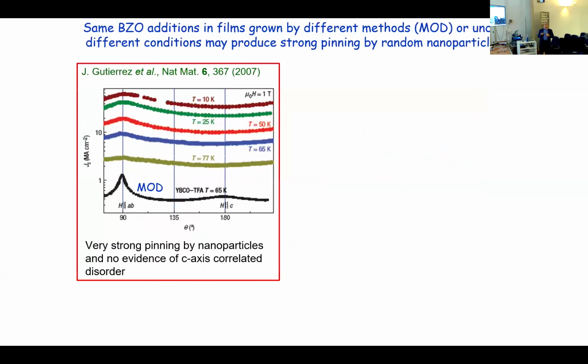Now, some people will be familiar with the pioneer work done here in 2007, showing that introduction of barium zirconate could also produce a very strong increase in the critical current. But in this case, not by nanorods, because nanorods didn't form in this layer-growth MOD, but instead form randomly distributed nanoparticles. So you don't see a c-axis peak here. However, the increase in the pinning is also extremely dramatic.